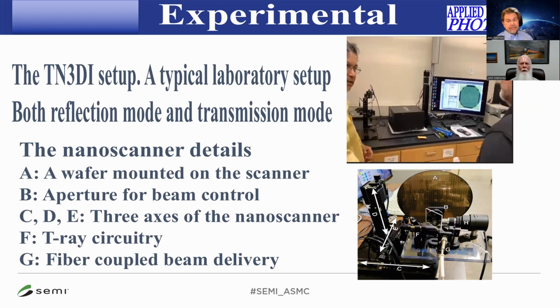Right. It certainly does provide a lot of flexibility. First of all, it always ensures vertical incidence on a sample. The sample doesn't have to be vertical all the time. It can be vertical, horizontal, or at any other angle as well. If I have a non-uniformly shaped sample, I can make sure of vertical incidence, because the fiber-delivered T-ray circuitry can be mounted on a rotary stage, and the rotary stage can be used to point the beam at whatever angle, and we have the software to determine the right angle for vertical incidence.